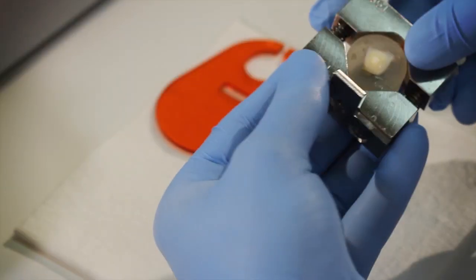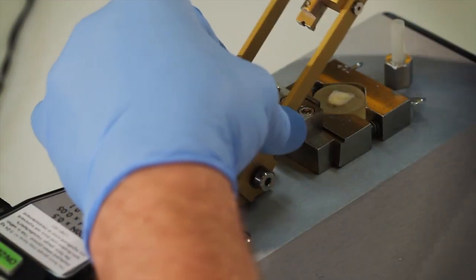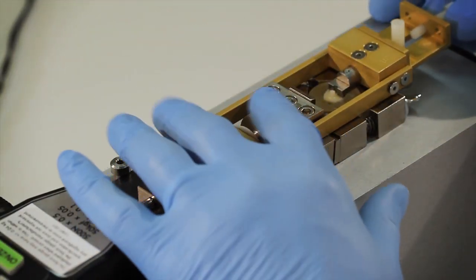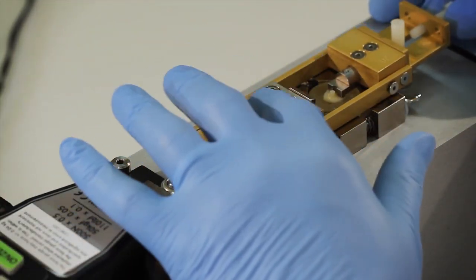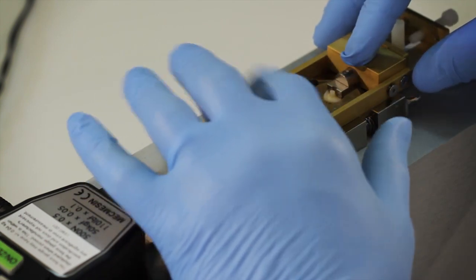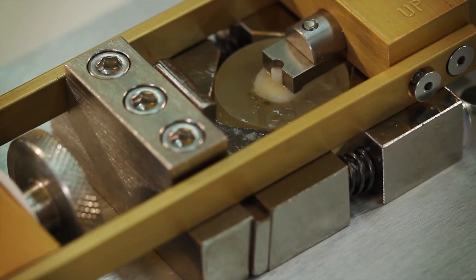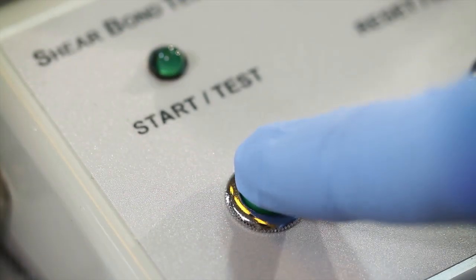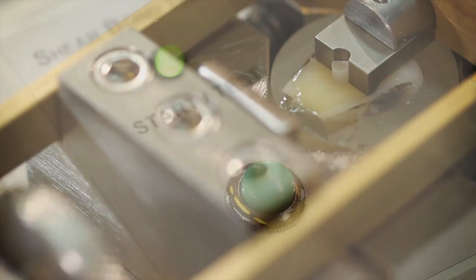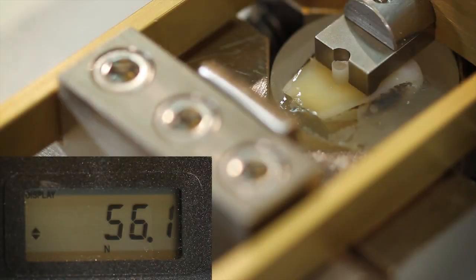Each sample was placed in a clamp and loaded into the portable shear bond strength testing unit. The wheel was slowly turned, bringing the shearing mechanism into contact with the composite. Once the start test button was pressed, the shearing force against the composite was gradually increased until the composite debonded. The force required to break or debond the samples was recorded in newtons on the electronic gauge.